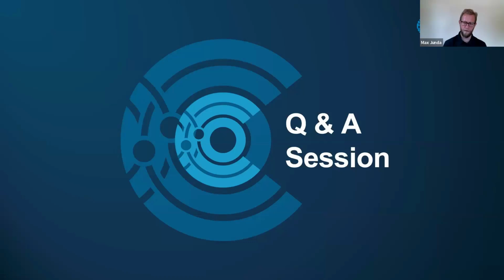Cool. Thanks, Lyle. Here's another actually really interesting and insightful question. In ellipsometry, is the surface roughness induced scattering, so this is what I talked about before, as the surface gets kind of rough, hundreds of nanometers of roughness, and you have scattering, is that scattering sort of incorporated into the derived K values, the absorption in the material, since scattering effectively increases the extinction? That's actually a great question.